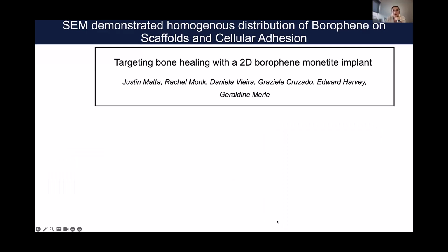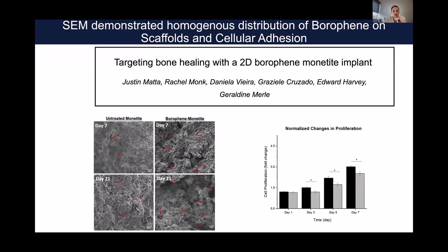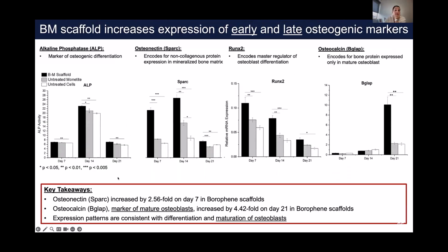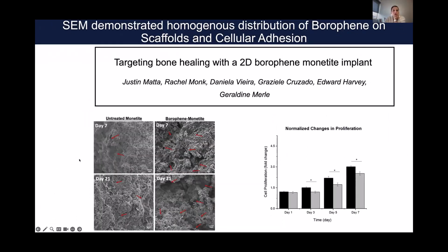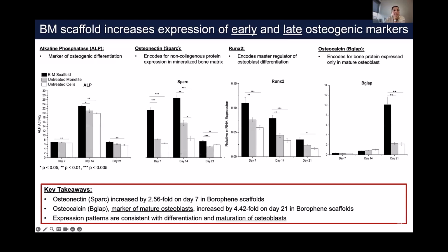Then we seeded some pre-osteoblast cells onto the cement, and we checked if it was biocompatible and if the cells were able to proliferate onto the cement and within. And this is what we saw. We saw a big difference between with and without the presence of borophene. And then we checked as well the expression of some genes specific to osteogenic differentiation and maturation.